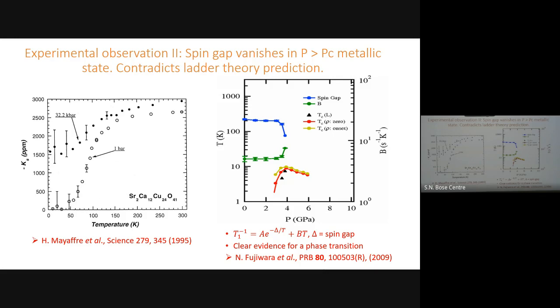Okay? All right. This is something else which also appeared in parallel. Remember, the appearance of the superconductivity was 96. One year before that, a French group, this group is very well known in the field of organic superconductors. Denis Jerome, who discovered TMTSF, etc. They did NMR measurement under pressure. This is Science. So you can see this is atmospheric pressure. This is the Knight shift. They're measuring the spin gap. The spin susceptibility shows this figure. That means the spin susceptibility goes to 0 because there is a spin gap. If I have a triplet-singlet gap, to get the susceptibility, I have to excite it, otherwise the susceptibility is 0. Sure enough, ladder theory works. But at the pressure where it becomes superconducting, the gap is non-zero. They wrote it and they said the same thing, that maybe this has got nothing to do with ladder theories.